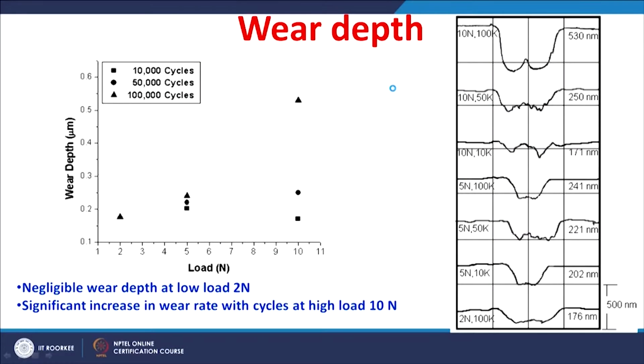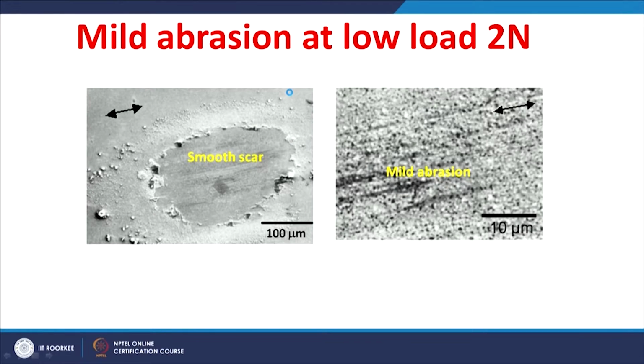So, the wear depth also indicates very important information. There is a negligible wear depth at lower loads of 2 Newton, but a significant increase in the wear depth as well as the wear rate at the higher load of 10 Newton. So, let us study the worn surfaces to understand the mechanism of material removal for the tungsten carbide zirconia nanoceramic composites. At a lower load of 2 Newton, you can see the wear scar is very much smoother, and